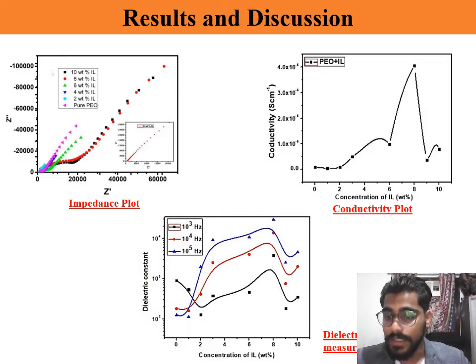Whereas, as we can see with the increase of concentration of the ionic liquid in our work, we can observe a change in the order of conductivity, and hence at 8 weight percent of ionic liquid we have an optimized and highest conductivity at 10 to the power minus 4 Siemens per centimeter. This sudden increase in our conductivity might be due to the increase of the free mobile charge carriers during the incorporation of ionic liquid in the PEO matrix solution.